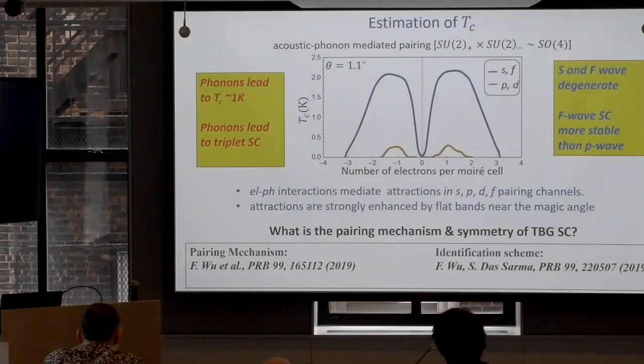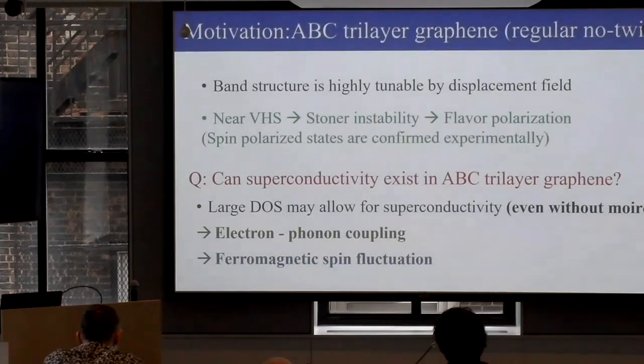electron-phonon interaction, symmetry, and Van Hove singularity interplay. Okay, so all these peaks going away, this all depends on the band structure. So this is a numerical calculation with the full band structure. But this is still twisted bilayer graphene. Now I'm going to talk about ABC tri-layer graphene.